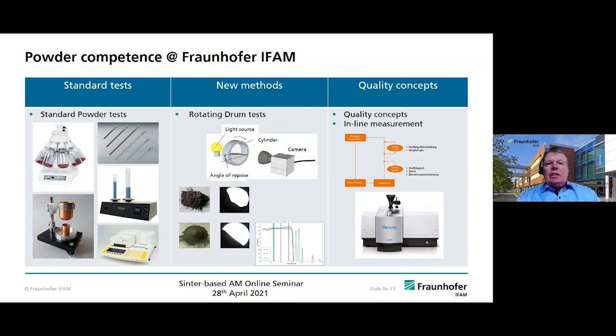Powder competence is always vital for these powder bed based processes like binder jetting. So there we use all the standard test equipment and standard test methods we have been using with our classical powder metallurgy technologies like MIM, like classical sintering. But we have learned quite quickly that with additive, you sometimes need more precise figures on flowability, for example. If you look at the lower left, you see this test setup for the classical funnel flow test, which has been standardized for decades, but which doesn't work for the fine powders we use with additive technologies.